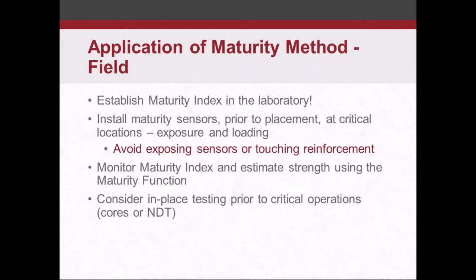That's an estimate. If you're doing some critical loading operation, maybe you don't want to rely solely on this maturity method. Maybe you want to put some field cure cylinders out there. Maybe you want to do some other non-destructive testing, maybe a rebound hammer or Windsor probe, or maybe you want to take cores if that's an option. But the biggest takeaway here is that the maturity method starts in the laboratory. So it's a great method. We've used it a number of times, and it's proven to be pretty valuable to a lot of contractors.